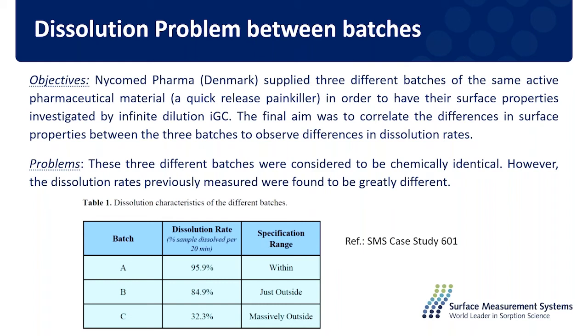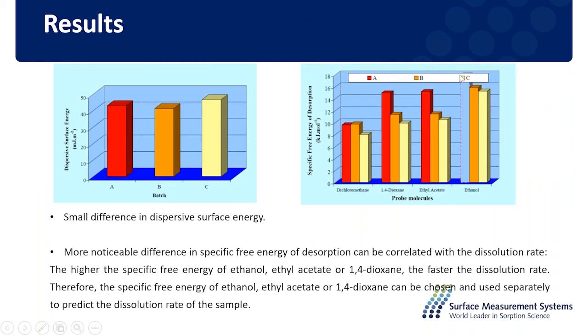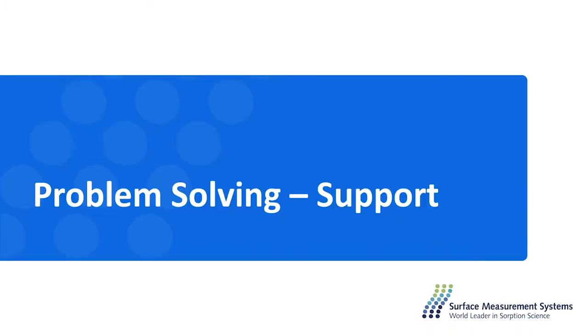And we measured the surface energy and the specific free energy of the different probes to see if there is any difference between those samples, because they couldn't see any difference with the other analysis techniques they used every day. And we could easily pick that the C batch has a really different dispersive surface energy, but it wasn't that significant. More significant was the specific free energy of the different probes in the case of the C batch. So we could easily distinguish the batch which was out of their expectation.